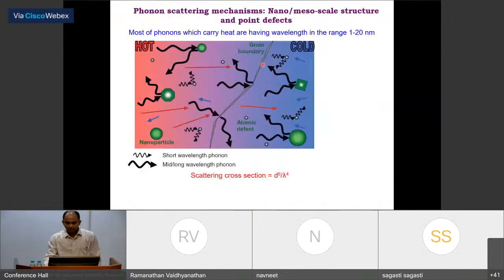From the 1950s and 60s, Russians worked in this field enormously, and they've shown that by solid solution point defects or grain boundaries, some of the phonons can be scattered, but those are not the important phonons. Those phonons have either very short wavelength or very long wavelength. But the phonon we need to scatter is basically 1 to 20 nanometer, for which we need a nano precipitate to be embedded in a solid matrix.